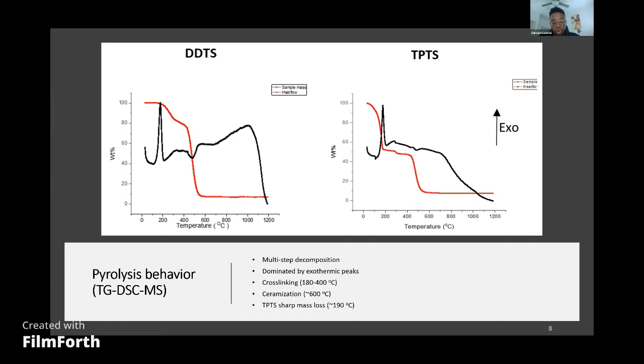Similarly, by looking at their DSC curves, we're able to see that most of the heat flow is dominated by exothermic peaks. The peaks that we observe around 180 all the way to 400 degrees centigrade can be attributed to the cross-linking of the polymeric precursors. Similarly, the exothermic peaks close to around 600 degrees centigrade can be attributed to the ceramization of the polymeric precursors.